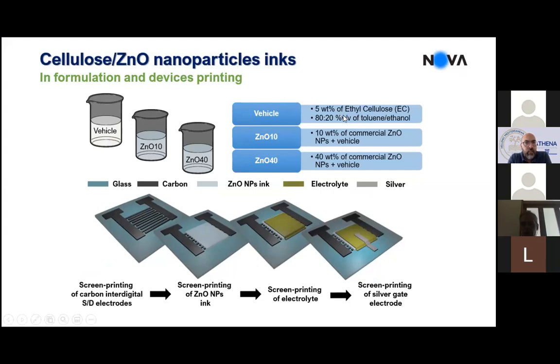So you go and modify it again, the cellulose, and you get a powder, in this case, that is soluble in alcohol or methanol, or ethanol, or a mixture of toluene and ethanol, or acetone is also possible. But as I said, we prefer to use CMC because it's a water-based system. In this case, we use zinc oxide nanoparticles to mix with the binder, okay? Because we want a semiconductor material or functional ink.